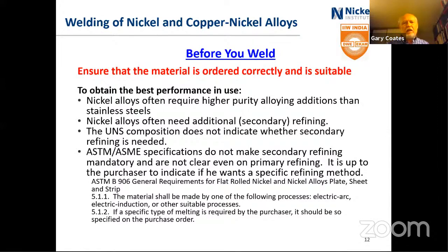So typically, nickel alloys require higher purity alloying additions than stainless steels. So not everybody can easily make them. More important, they often need additional refining, and I'll come back to what that exactly means, but secondary refining. And unfortunately, the UNS composition doesn't indicate anything about it. Even ASTM, ASME specifications do not make it clear whether secondary refining should be mandatory or not. And they don't even talk about the primary refining in any degree. So it's really up to the purchaser to indicate if he wants a specific refining method, including a secondary refining of it. And I just quote a little bit of ASTM B906 there, which is for a general requirement for nickel and nickel alloy plate, that it really tells you nothing, to be honest.